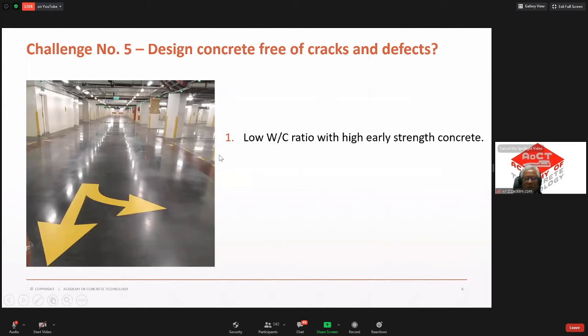So playing around with this, what we found for the mix design is, if you can, keep your water between 145 to about say 180 kilos per meter cube. That's subject to your cement again. That's very important. Another thing, even too much cement could be bad, because we always try to cap our cement content below 400 kilos per meter cube of concrete. The reason is if you've got any higher cement than that, it might cause curling of floor slab. The slab will actually curl up. So that's another type of defect.